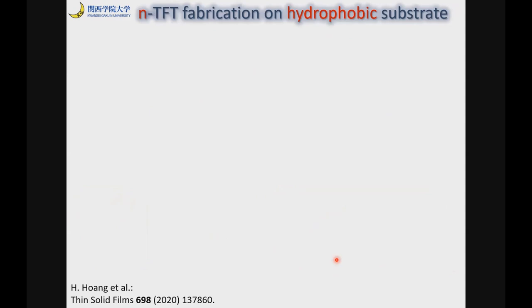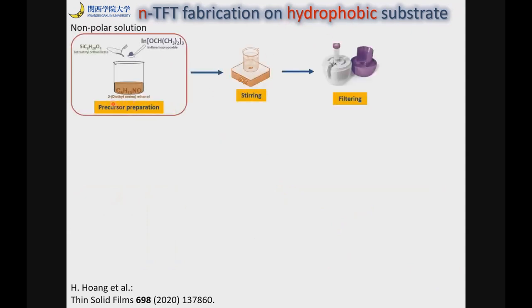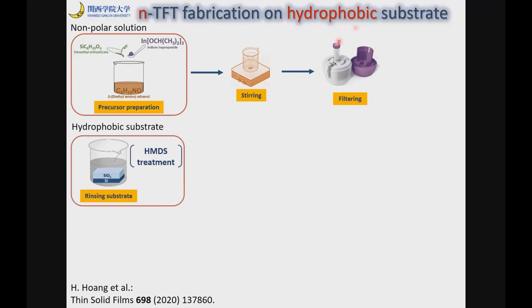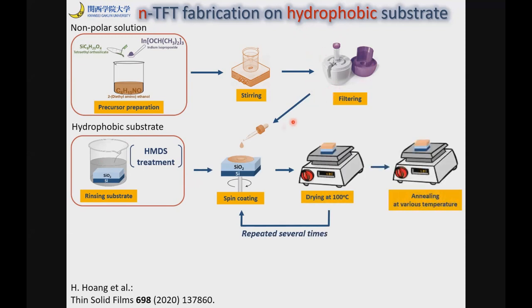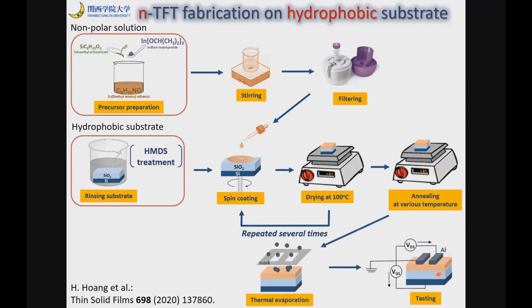Okay. So let me move to our experiment. First we try the N-type TFT fabrication on hydrophobic substrate. Therefore, we need to make the non-polar solution. I won't discuss the details of the materials, but we put the raw materials into the non-polar solvent, stirred and filtered. For the hydrophobic substrate, we treat the substrate with HMDS. Then the filtered solution is put onto the substrate, spin coated, dried, and formed into a solid thin film by annealing. After that, we fabricate the devices.